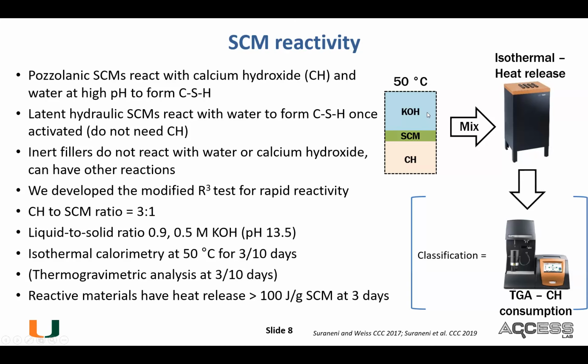So essentially, these supplementary cementitious materials, as I mentioned, for the most part, are amorphous calcium aluminosilicates. They're now putting them at high pH. A lot of people are surprised by this, but traditional cement pH is about 13.